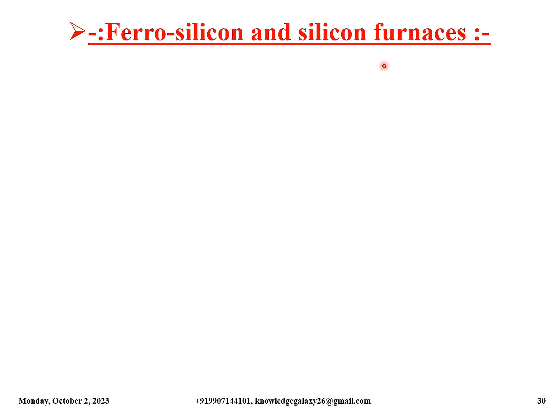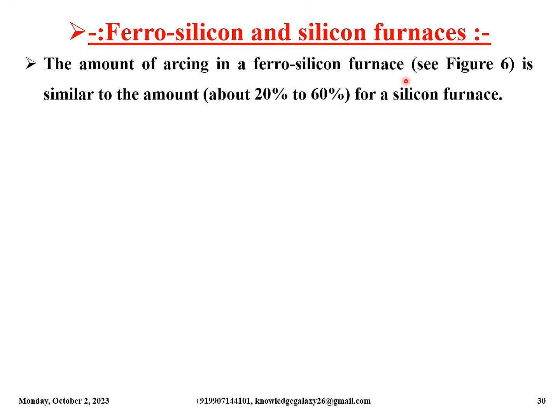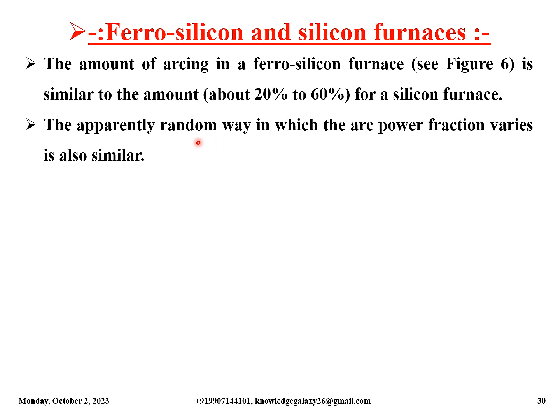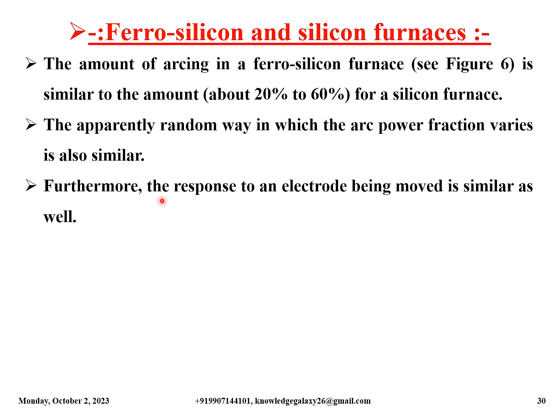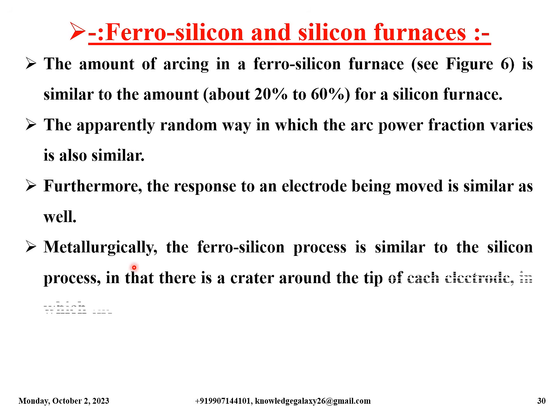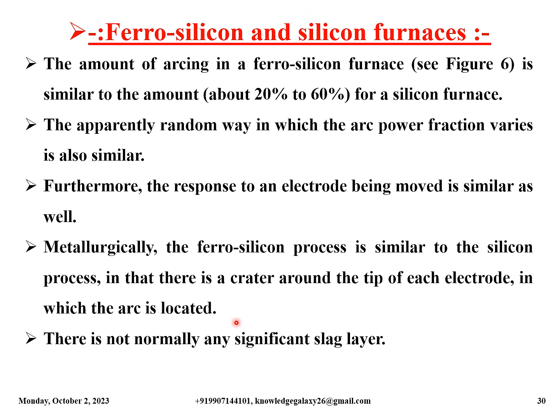Ferrosilicon and silicon furnaces, let us have some points in detail. The amount of arcing in a ferrosilicon furnace, about 20 to 60%, is similar to that for a silicon furnace. The apparently random way in which the arc power fraction varies is also similar. Furthermore, the response to an electrode being moved is similar as well. Metallurgically, the ferrosilicon process is similar to the silicon process in that there is a crater around the tip of each electrode in which the arc is located. There is not normally any significant slag layer.